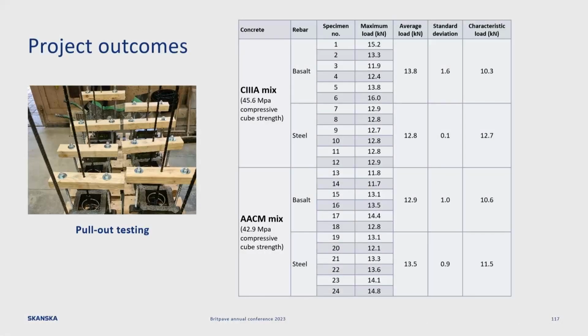Pull-out tests. We did our best to meet the British standard for this with the steel coils that you can see within the sample. But unlike the basalt fibre reinforcement that you can see outside in the entrance, these bars had a helical strip attached to the outside of the bar after the pultrusion process. So it's essentially welded to the outside of the bar using the polymer. The bars outside are sand coated, and I'd be very interested to compare the difference in performance between the helical bar and the sand coated bar, because we did see some slip in these results.